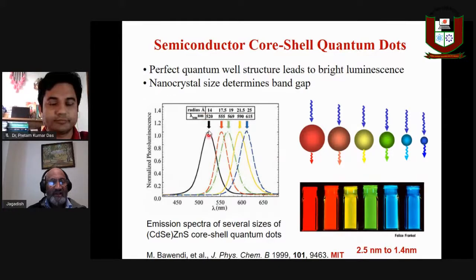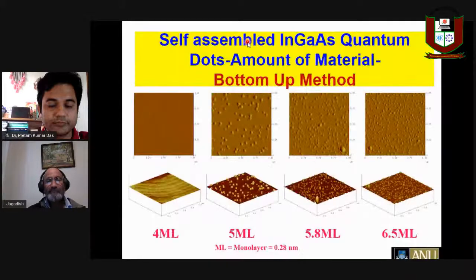These structures are really, really small: 1.4 nanometers, 1.75 nanometers, 1.9 nanometers. These are in angstroms, or 2.15 nanometers or 2.5 nanometers. As you can see, by changing these from 2.5 nanometers to 1.4 nanometers, they're able to tune the emission wavelength quite significantly. In fact, these sorts of quantum dots are currently used in TVs and other things as well.